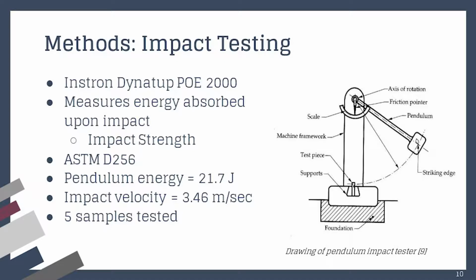And it's important to note that this was a standard machine, so each time we had the impact, the pendulum energy had a value of 21.7 joules, and the velocity was 3.46 meters per second.